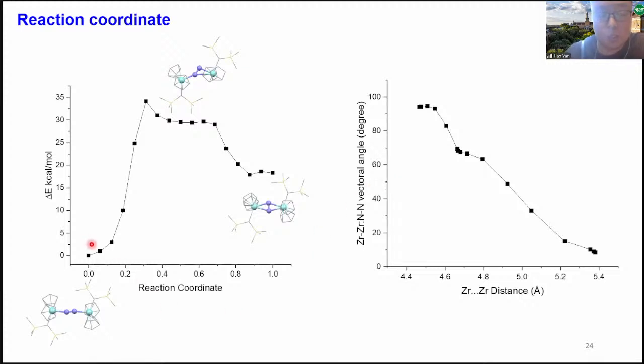The first thing we calculated is the reaction coordinate. We used the nudged elastic band, or NEB, method. And what we found is that this transition actually has two saddle points, starting from the side-on structure.